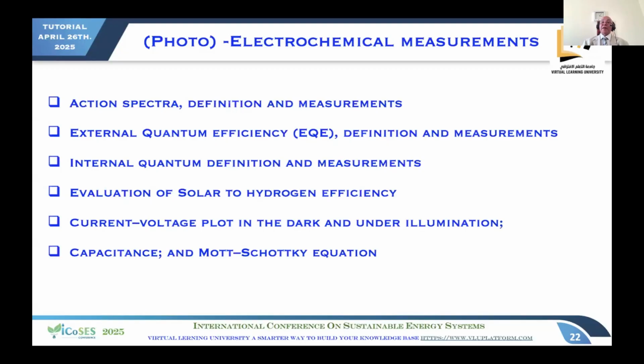So they are able, and as Thomas Hannabel said yesterday, device equals interface. So there are a lot of interfaces. So if you use III-V compound, you have already three interfaces plus the interface with the electrolyte, 2, that means 5 interfaces. And therefore, that's the challenge, how to collect the whole spectrum. And the second challenge is the kinetics. If the kinetics is very slow, then the electrons, if they can't go to the reaction, they will recombine, and then you can lose something in the current.